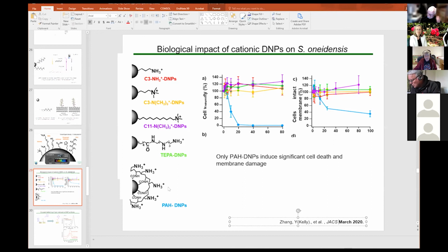And actually what we hypothesize is that the reason these polymer modified nanoparticles are much more toxic is the polymer wrapping is kind of, I won't say incomplete, but when a polymer wraps around a particle, it has what are called loops and tails. So regions of the polymer that extend out further into the aqueous medium. We have another paper that was just provisionally accepted last week that'll be in print in Langmuir next week, characterizing these same molecules using vesicles and showing that in fact we can characterize that interaction of the vesicle in the same way. So it's really that these polymer wrap particles have these things that are sticking out that can then intercalate between the lipid bilayers of a cell membrane, and that is the mechanism of toxicity.